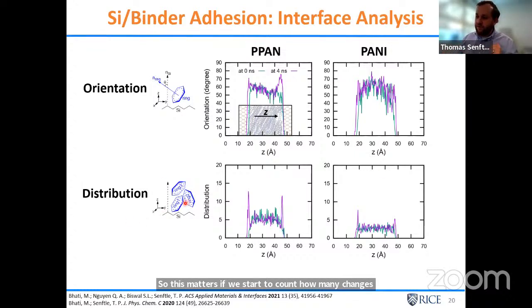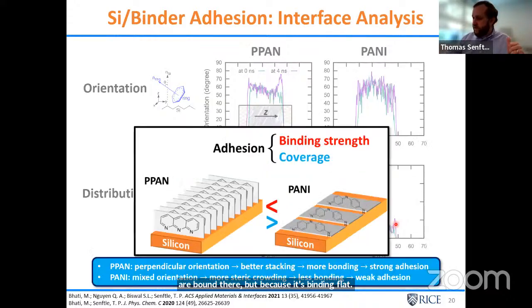If we look at a distribution of just the number of rings bound onto the surface, we see that p-pan has these large spikes, meaning a lot more chains are getting down onto the surface. The polyaniline, we get a little bit of spikes at the surface, meaning there's more chains that are bound there. But because it's binding flat, you basically get really strongly bound chains that block all the other chains. So the picture that emerges is that although each individual chain of p-pan binds weaker than polyaniline, you get a lot more of them down on the surface because they can stack themselves up.